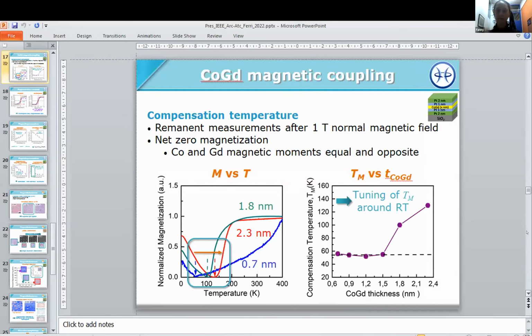Just remember that all these measurements are done at remanence, so without applied field. So when we increase the temperature, the total magnetization decreases, reaches 0, and then increases again. And so this minimum is the compensation temperature. After 1.5 nanometer, when we continue to increase the thickness, you can see that this compensation temperature increases a lot, and maybe we can even reach room temperature.